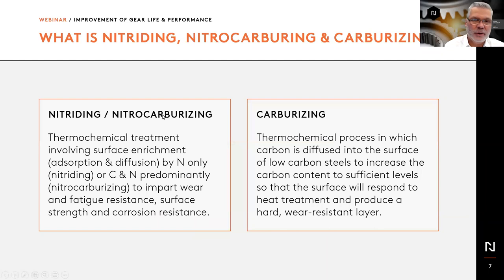Thank you. So what is the biggest difference between nitriding, nitrocarburizing and carburizing? Both treatments are thermochemical treatments. They rely on different mechanisms. In nitriding, the surface is hardened and modified using adsorption and diffusion of nitrogen. This modifies chemically the surface, but does not really change the core of any part or any component.